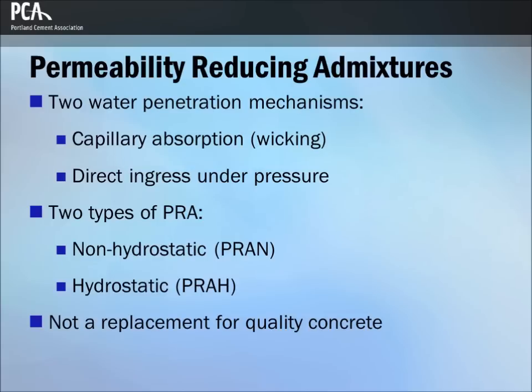Common materials include soaps such as stearates and other long chain fatty acids or other derivatives, as well as petroleum products. Hydrostatic permeability reducing admixtures have often been referred to as waterproofers, although permeability reducing admixtures for hydrostatic conditions is a more technically correct term. PRAs contain materials that act to block the pores and capillaries in concrete, and products usually consist of hydrophilic crystalline materials that react in concrete to produce pore blocking deposits or polymeric materials that coalesce in the concrete's pores.